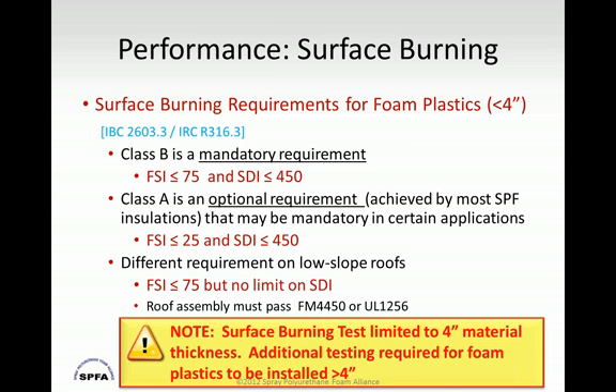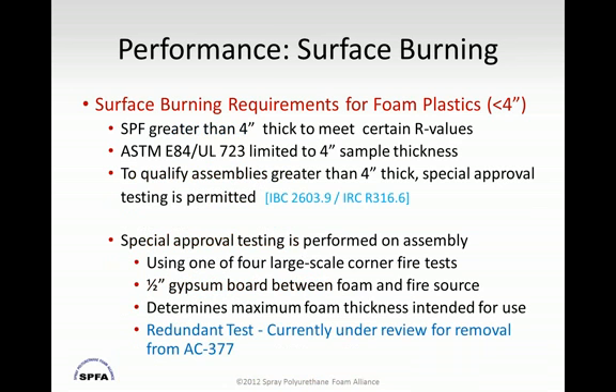Now, one of the things that we often see, and remember, getting back to that Steiner tunnel test or ASTM E84, is that the surface burning test is limited to 4 inches of material thickness. Right now, in the code, there is some additional testing required for foam plastics to be installed at greater than 4 inches. Right now, for the surface burning requirements for foam plastics greater than 4 inches, special approval testing is permitted. Traditionally, to allow foam to be at a thickness greater than 4 inches, most of our suppliers, or nearly all suppliers that have foam rated at 4 inches, have done one of the large scale room corner fire tests.